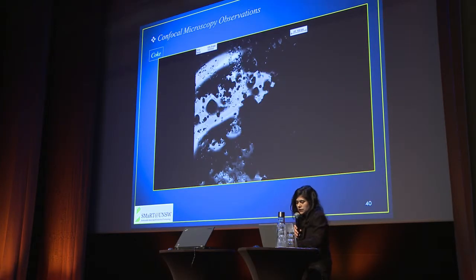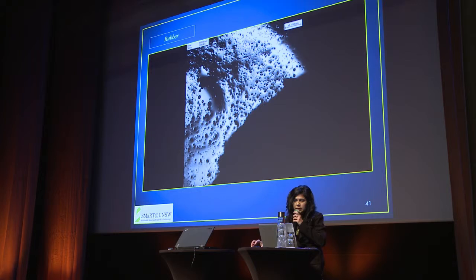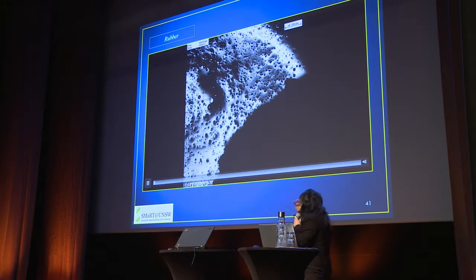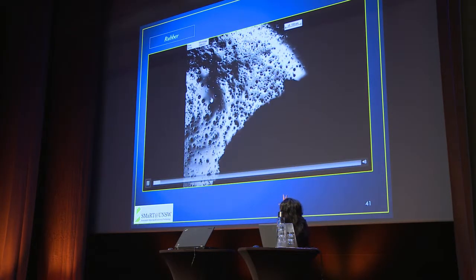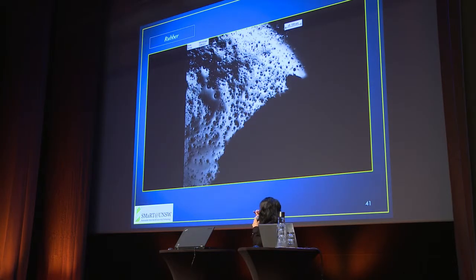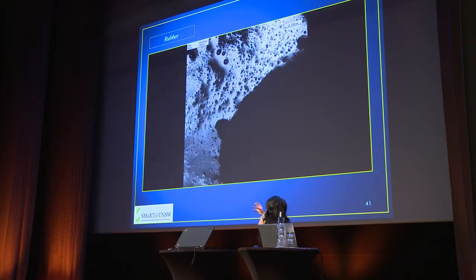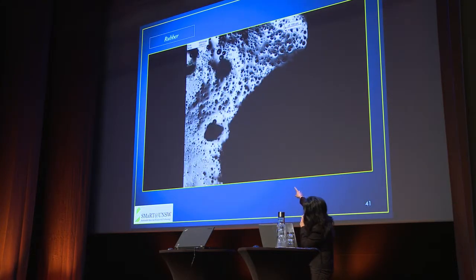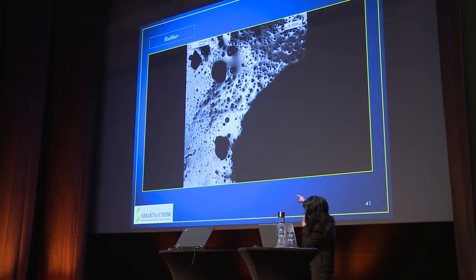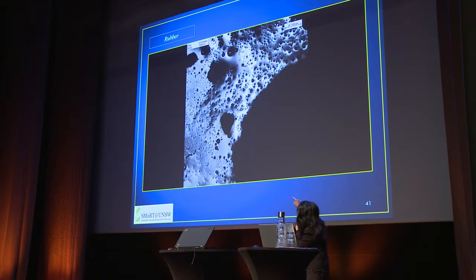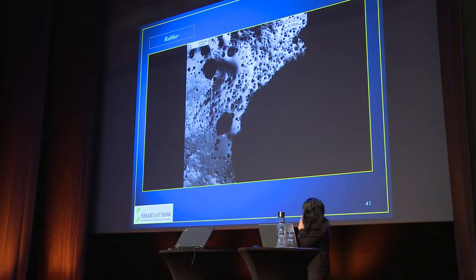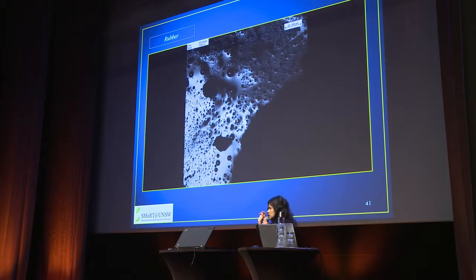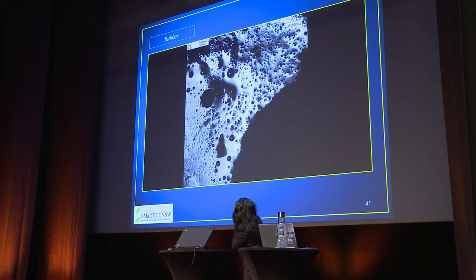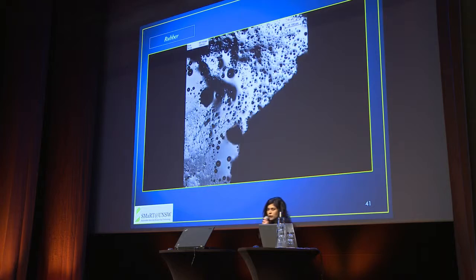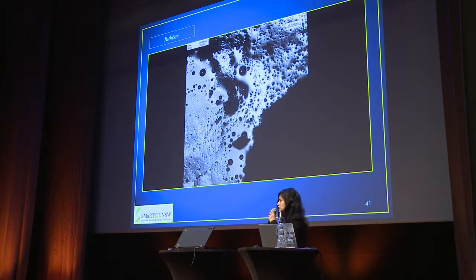In contrast, if you go back and see the difference now, and I'll play exactly the same video, when we brought rubber in contact with the same slag, you can see that you now no longer have those massive explosions of gas bubbles. You can actually see the dark particles are basically rubber particles interacting with slag, and where the rubber particles are interacting with slag, you can start to see these really minute bubbles coming out as a result of these high temperature transformations.